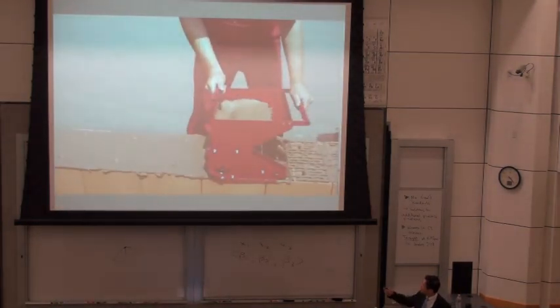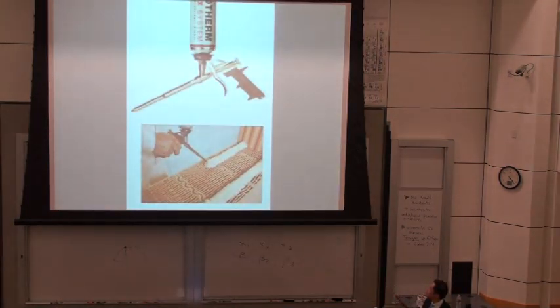The more modern way is to use the so-called thin bed mortar. Thin bed mortar is just 1 millimeter or even less than 1 millimeter. It's like a glue, therefore the blocks need to be ground. So the accuracy of the blocks is more or less 0.5 millimeter. And the newest invention is a glue based on polyurethane. So it's no mortar at all, no cement at all. You just apply 2 lines of this glue and put these blocks together.